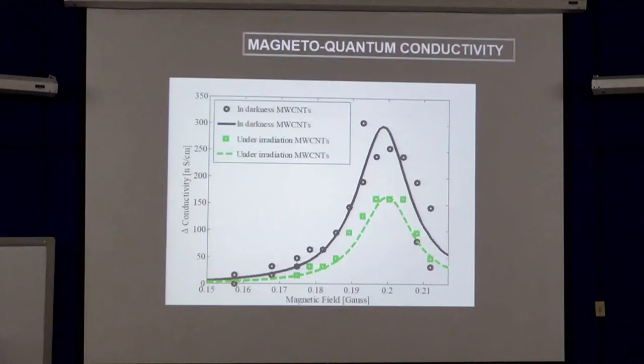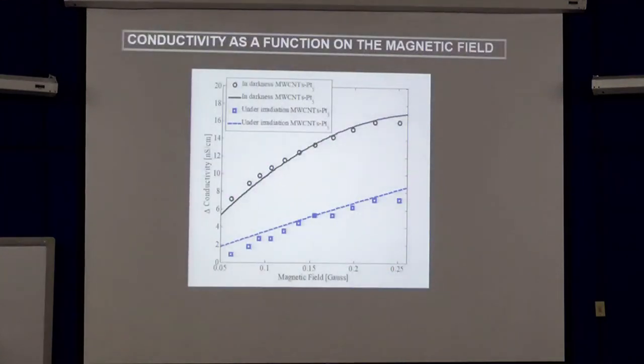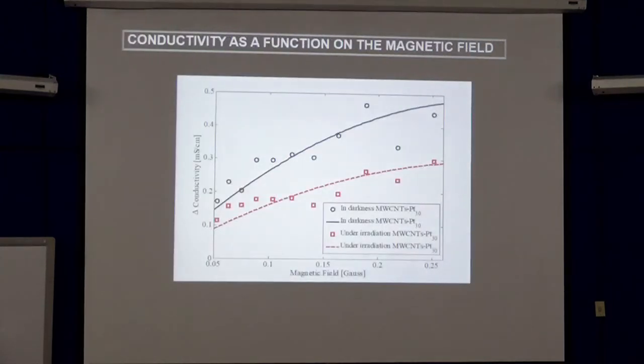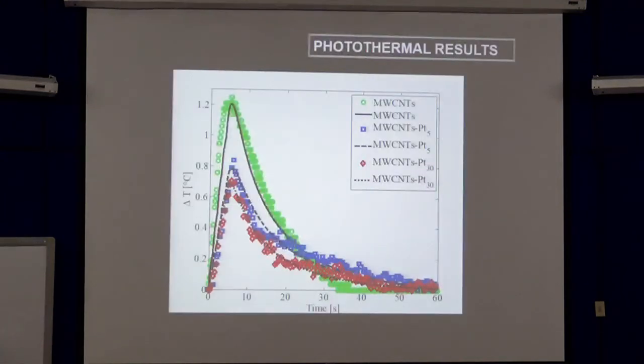This is without light. But with the decoration of the platinum nanoparticles, you can modulate the response of this conductivity. It depends on the amount of nanoparticles that you put in the nanotubes to change this effect.